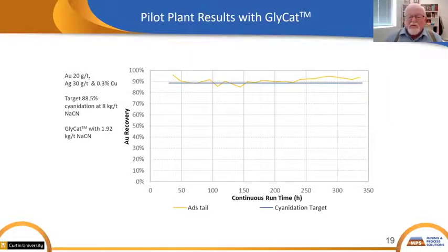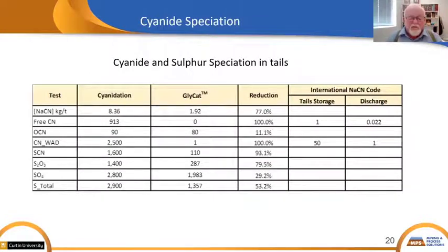So here's a table that shows something about the speciation of what happens. And in this case, we're able to show that in actual cyanide, we're able to reduce it by 77%. The cyanide in the tailings is down to 0, a 100% reduction. And you can see the rest of the things. The WAD determination is down by about 100%, from 2,500 down to 1%. And there's various decreases in other anions that you can see.